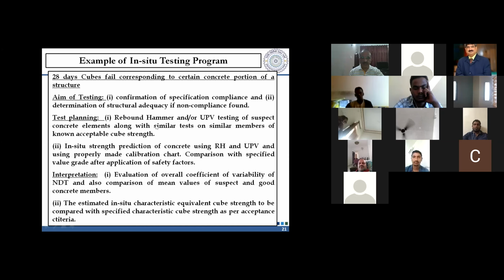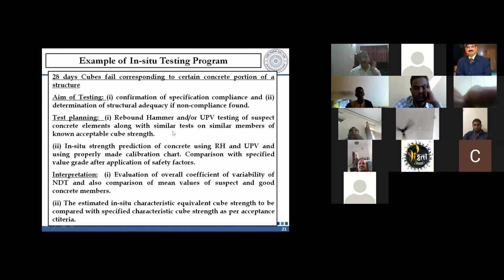That will also be found in order to check the compliance. Now, interpretation you will find out using this first. You have rebound, RH, UPV values for good concrete, for the suspect concrete portion and for the acceptable portion, for both. You will draw the histogram for the combined values.